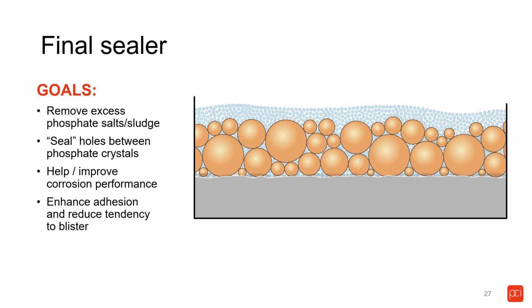As far as corrosion performance goes, using a sealer is going to boost the performance of any pretreatment that you use, with the exception of zirconium. Zirconium doesn't require a sealer. But with an iron phosphate, with or without a sealer, you're going to see a big difference between with sealer versus without. With zinc phosphate, the gap's a little bit closer.